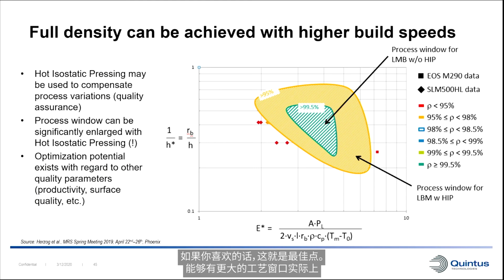So this gives you an enormous opportunity to increase the laser speed or the hatch spacing or the layer thickness of the material. So to play with producing parts with porosity in order to then subsequently HIP them, heat treat them in the HIP, and improve the material properties. So the sweet spot, if you like, the ability to have a look at a bigger process window is actually proven already and can be used to increase the speed on the parts.